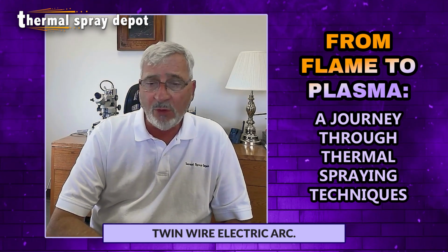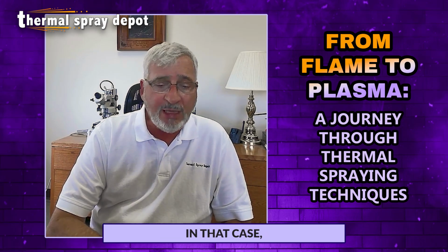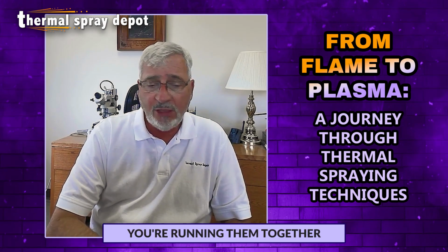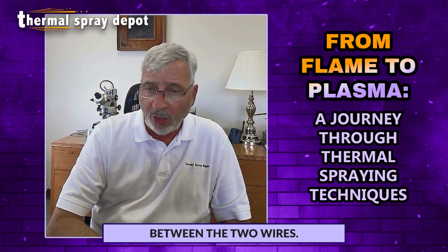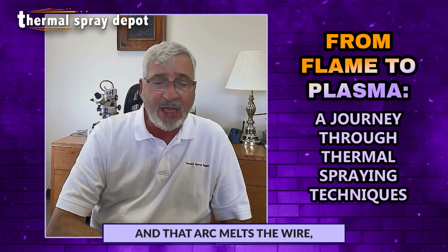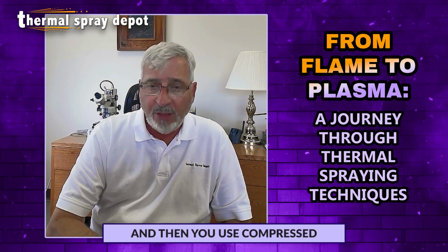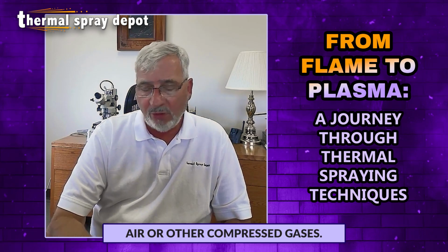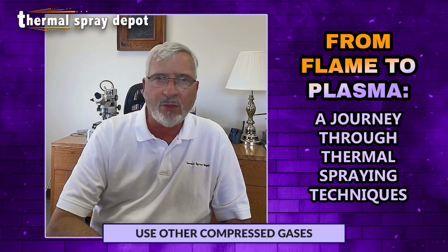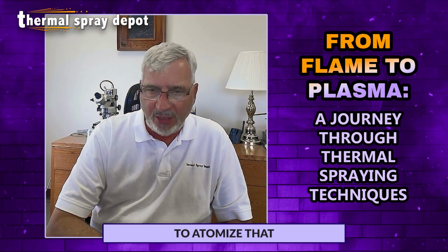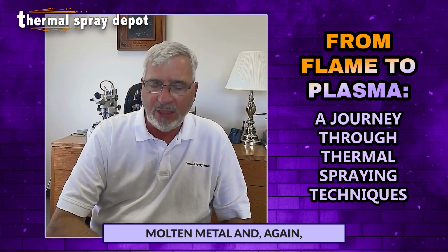You also have what's called twin wire electric arc. In that case, you're taking two wires, running them together and striking an arc between the two wires. And that arc melts the wire. And then you use compressed air or other compressed gases to atomize that molten metal and again create the spray.